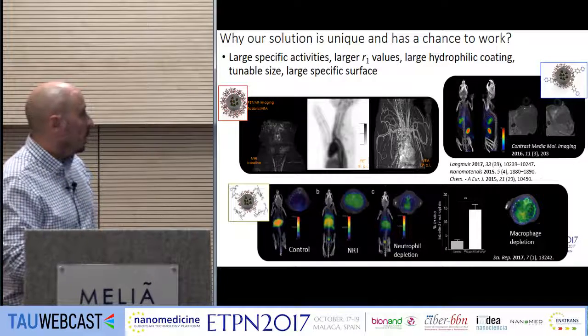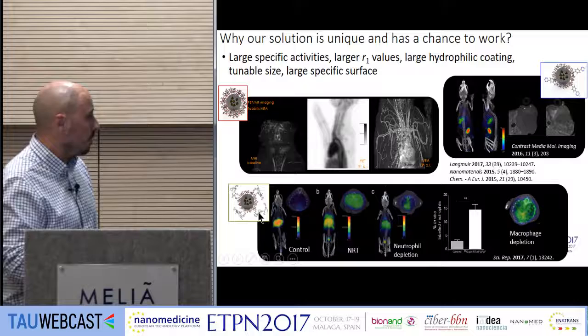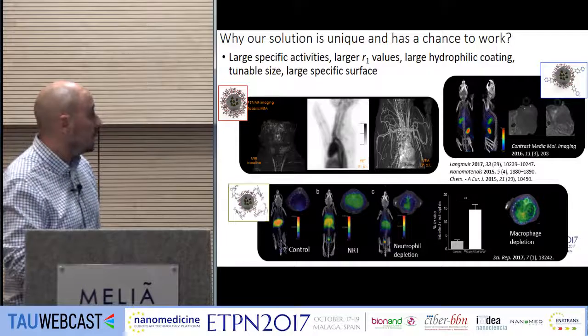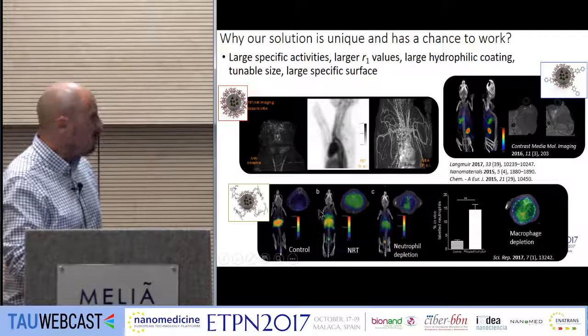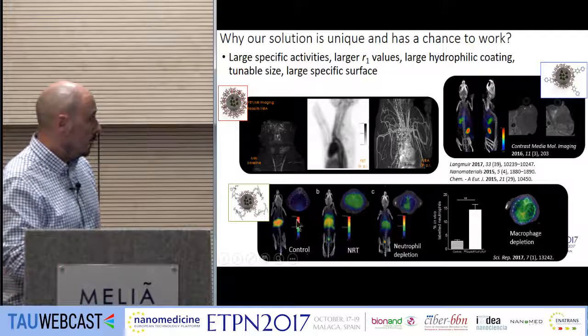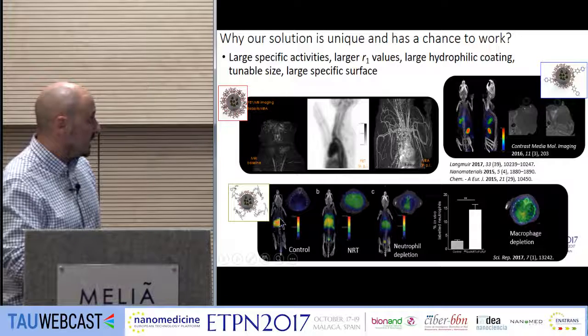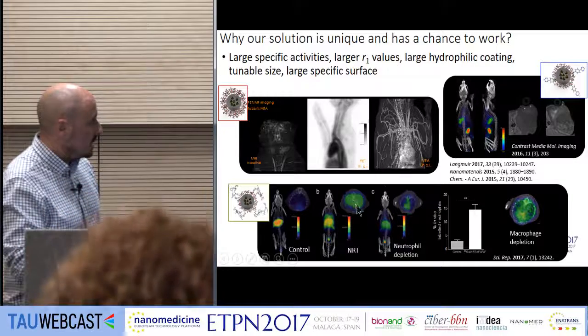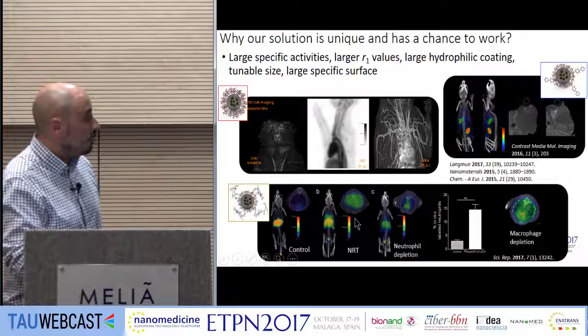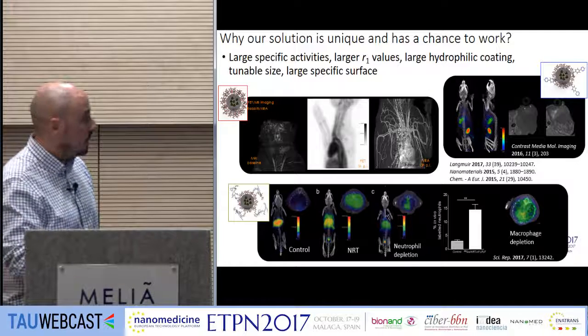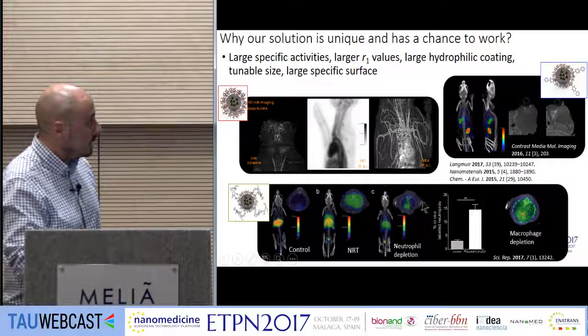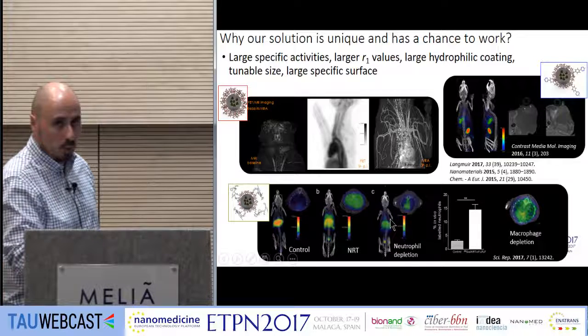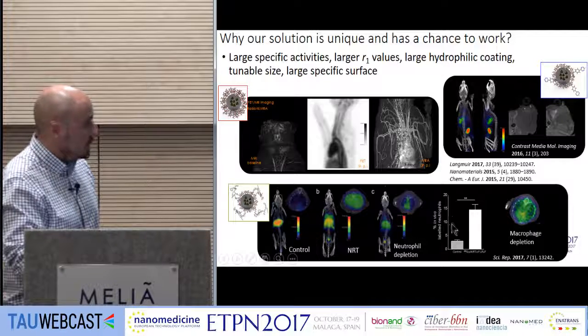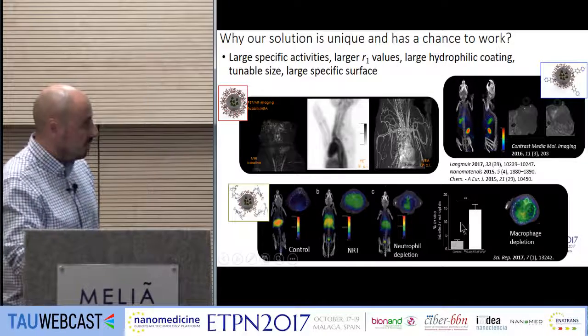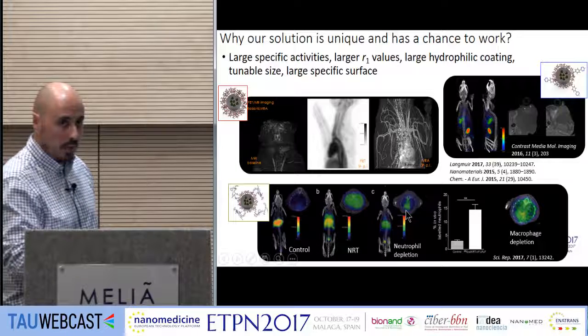The most recent approach, we have functionalized nanoparticles with an extremely hydrophobic peptide that is specific to neutrophils, and we have used it in an inflammation model in the lungs. If you use control mice and inject the nanoparticles, there is only signal in the liver, there is no signal in the lungs. When you use the functionalized nanoparticle, a quite large signal in PET in the lungs. If now you do the same experiment, but with depletion of neutrophils, the signal in the lungs disappears. This is the heart. There is no signal in the lungs because there are no neutrophils there. This is the percentage of in vivo labeled neutrophils. Up to 50% of neutrophils in the lung have been labeled with the nanoparticle.